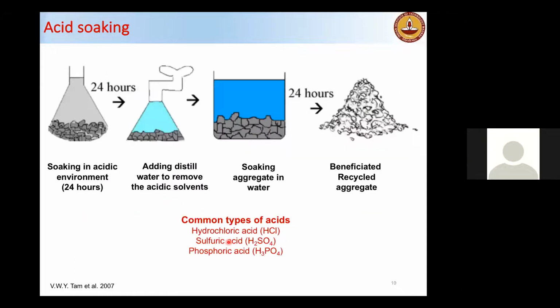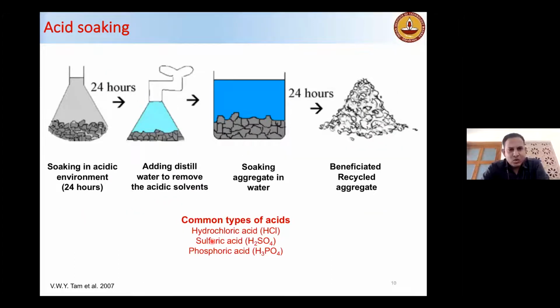Next is acid soaking. In this, RCA is soaked in acid for 24 hours, and then water is added to remove the acidic solvent or the corroded part of the aggregate. So granite or the other aggregate are more stable, whereas the mortar is prone to the acid corrosion. So it is dissolved and it is removed, and then it is soaked in water, and then what you get is the beneficiated recycled aggregate. Common types of acids used are HCl, H2SO4, phosphoric acid, and usually 0.1 molarity is used.